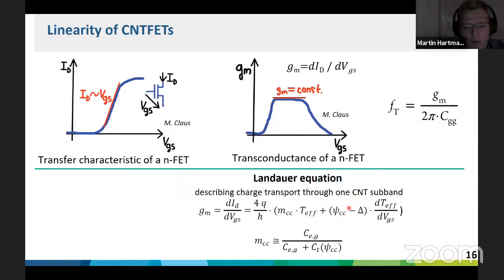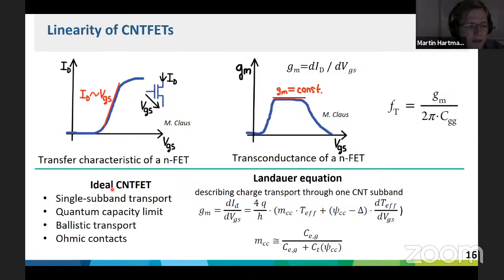equation, by the transport through one sub-band. This is a rather long equation. I will not go into any detail here, but within an ideal CNT FET, you have single subband transport, you have ballistic transport, ohmic contacts, and a quantum capacitance, or you can operate them in a quantum capacitance limit. This is what some papers or some theory and easy theory tells you.